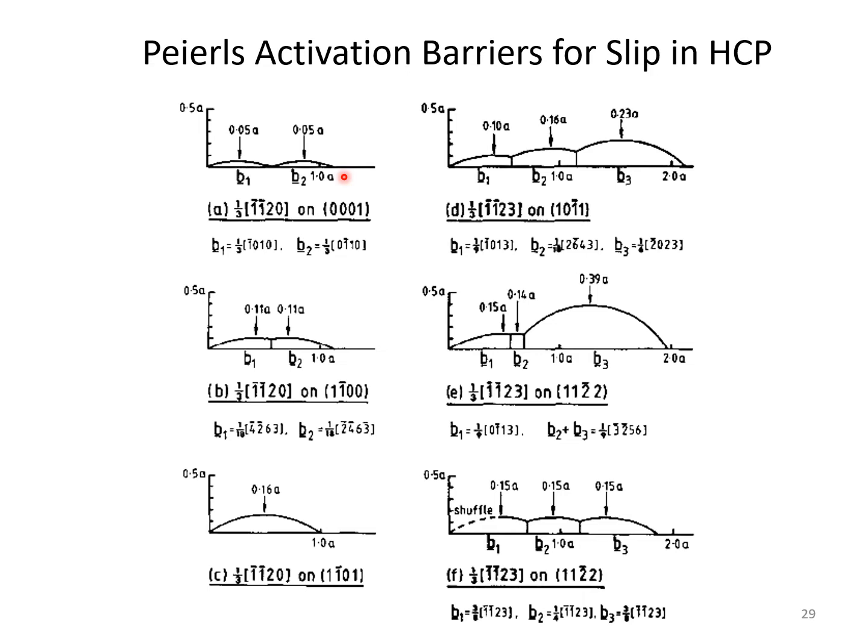But we can glide on prism planes. I mentioned how prism planes can be the most close packed planes. And in fact, for zirconium, this is the most likely plane at which you would get deformation. In this case, although there is a little bit, there's no intermediate site where the material might rest. In the other case, you might get a situation where a material will deform a little bit, and the atoms shear and then sit there, and they're happy to sit at this point. In which case, what you end up with is creating a stacking fault.